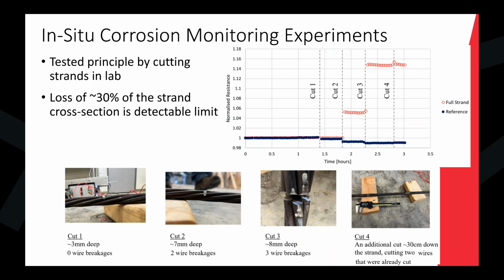We didn't go through any of the wires composing the strands completely. Cut number 2, we started to completely separate a couple wires. But really, by about the time we lost about 30% of the strand cross section, which is cut number 3, you're seeing the difference between those red data points and the blue data points. And that's a measurable difference.